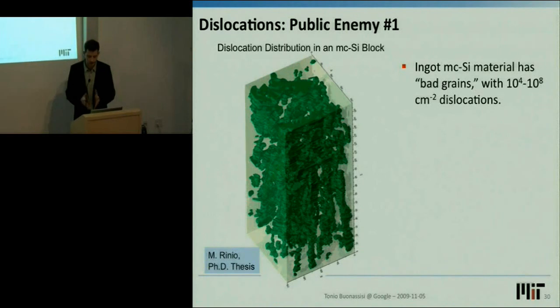And these are zones that contain dislocations, which are essentially one-dimensional line defects within your material, on the order of 10 to the 4 to 10 to the 8 dislocations per square centimeter. Anybody who's worked with integrated circuits or light-emitting diodes, for instance, knows these are very, very high values, very detrimental for electronic properties of a semiconductor material.